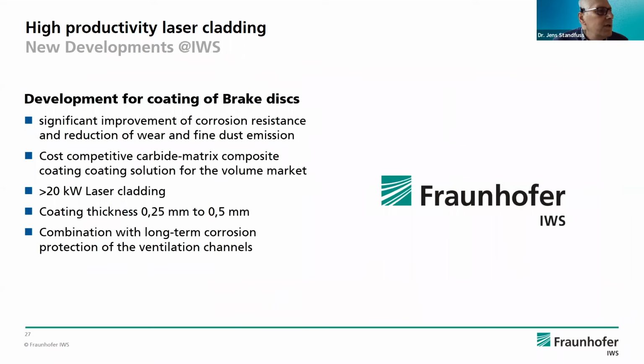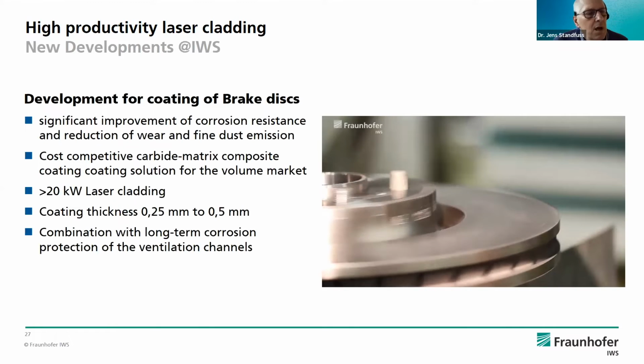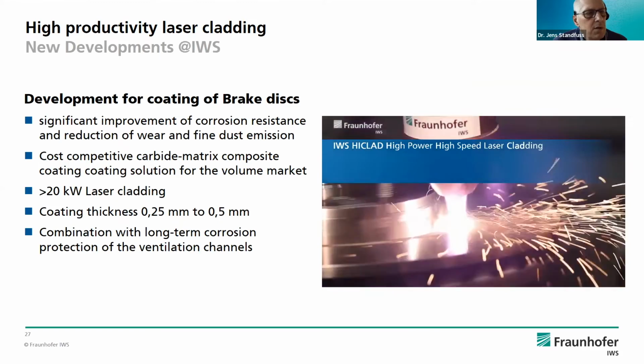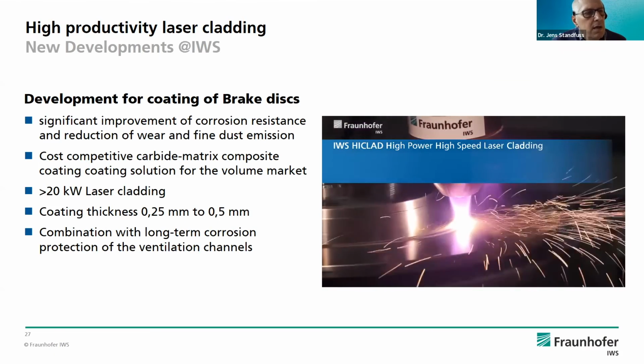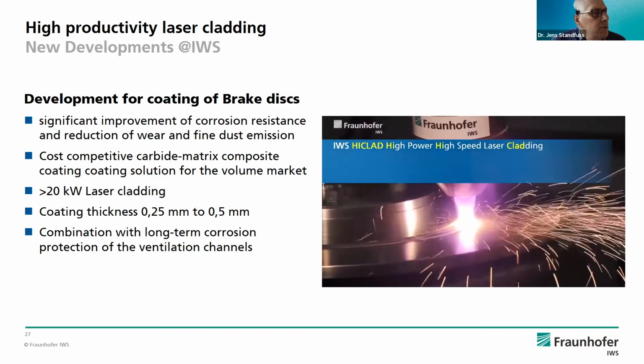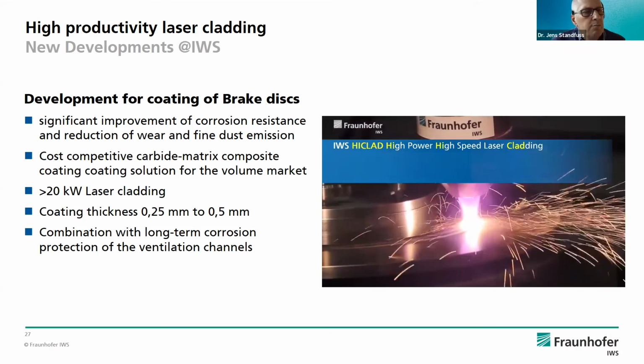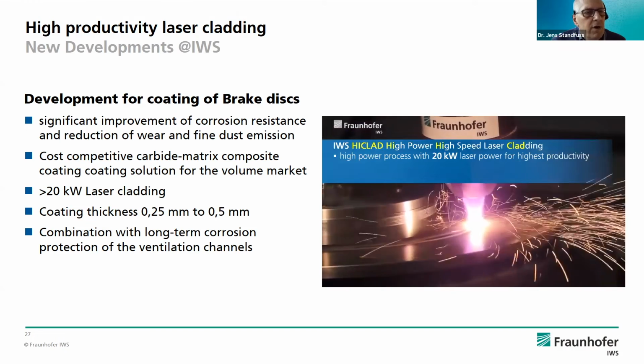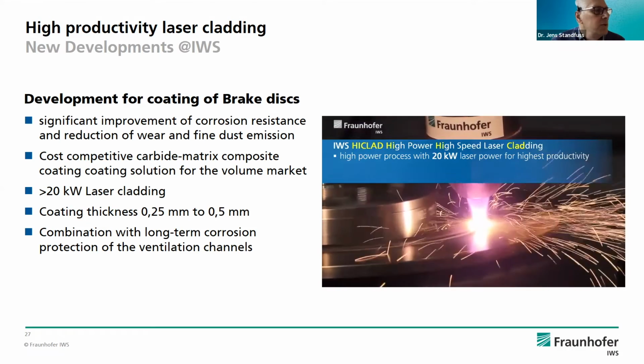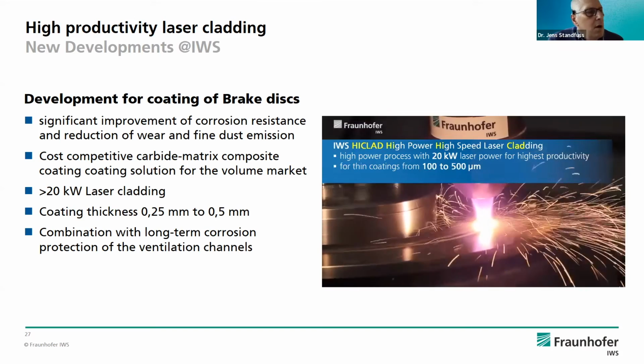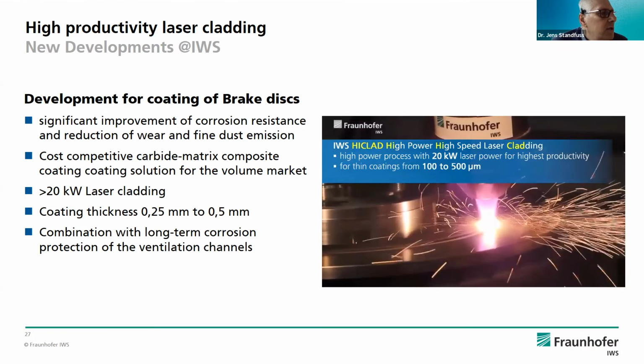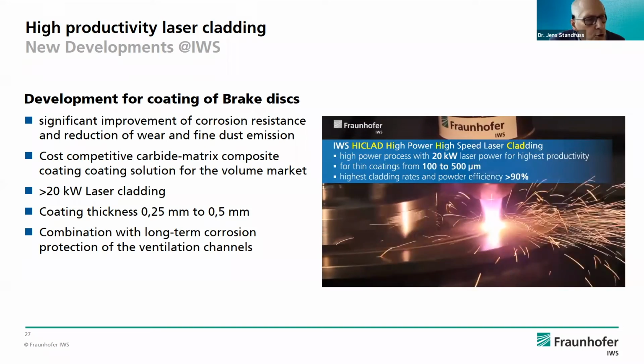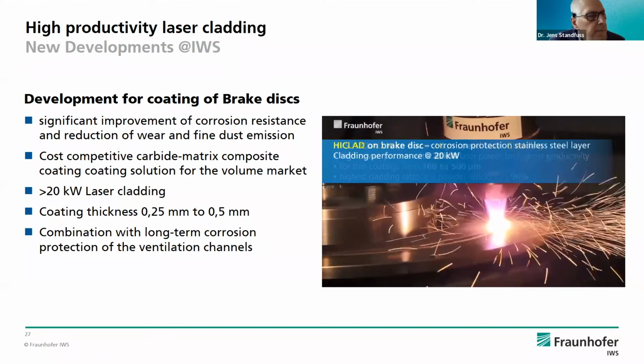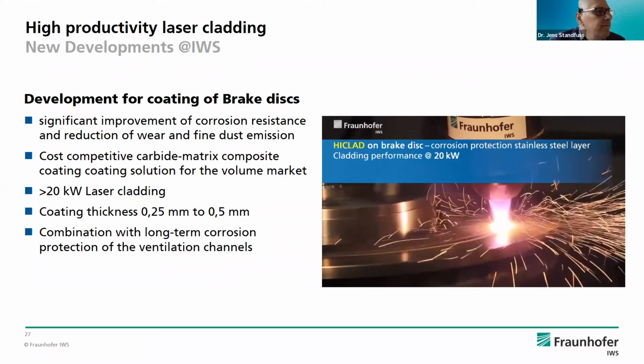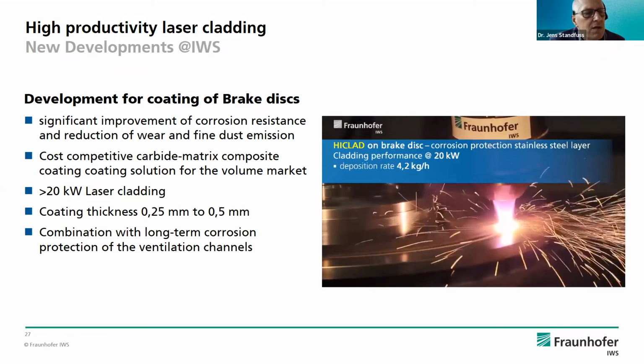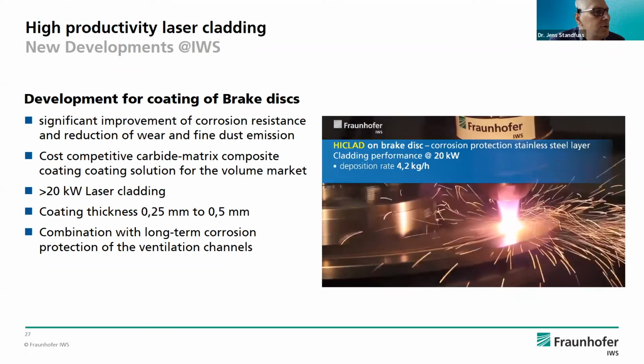How it works: now you see this HICLAD process with a high dynamic beam at high speed, using laser power up to 20 kilowatts, and you get a very high productivity with this process. The coating thickness is around 0.25 to 0.5 millimeter, and you have a good combination of long-term corrosion protection of this part.